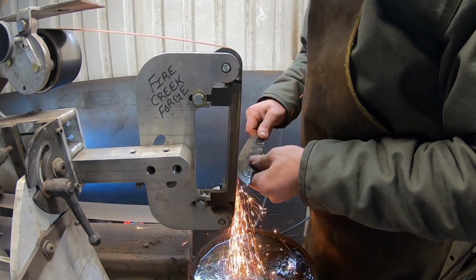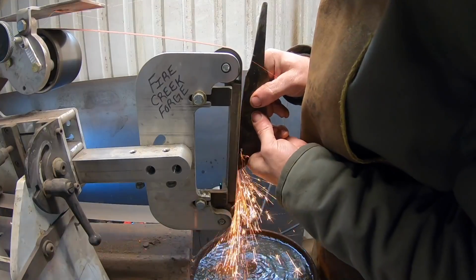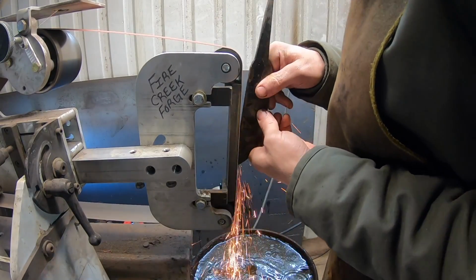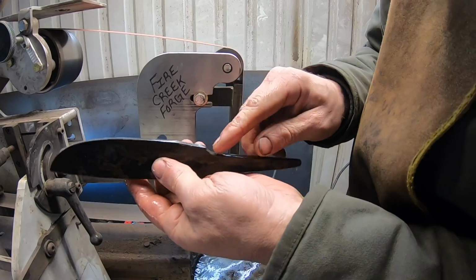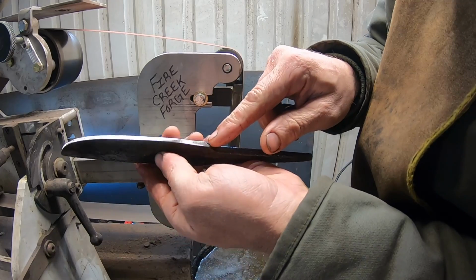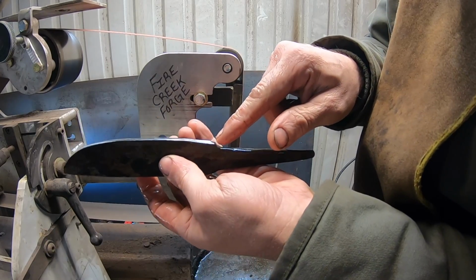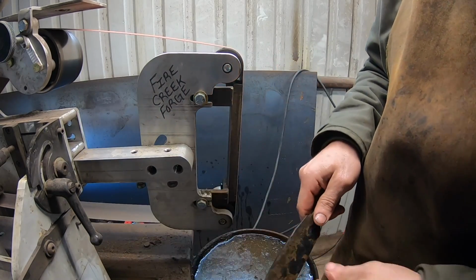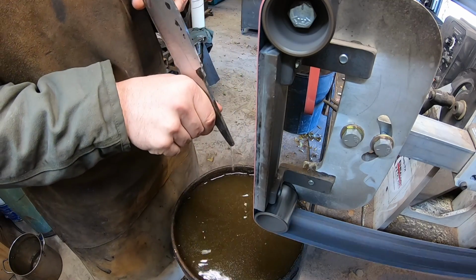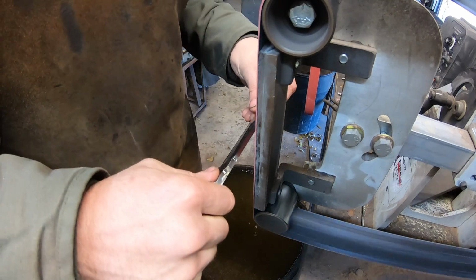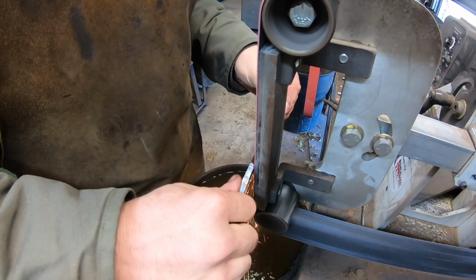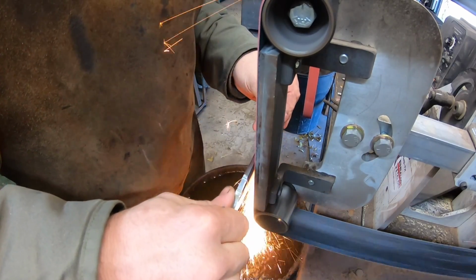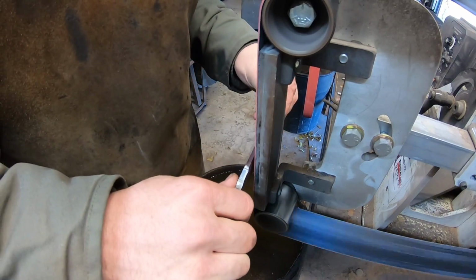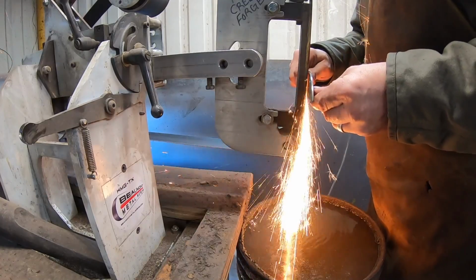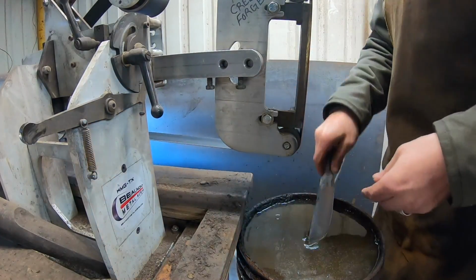Start by cleaning up the profile on the grinder. And it wasn't too long before I noticed that we still had some D-lam right here in the middle of the blade. That was concerning, because if that goes all the way through our edge steel, that could end this project right here. But fortunately, I was able to grind it out and kept most of the blade. So we still have a great blade profile and got that ground out to where we don't have any D-lam left on the edge there.